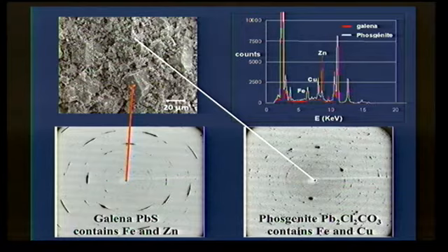But now, if we look at the fluorescence emission over this area for that particular phase, we find that the impurity content is completely different. So we have clear evidence, by looking at the impurity fingerprint, that those two materials have different origins, different provenance.